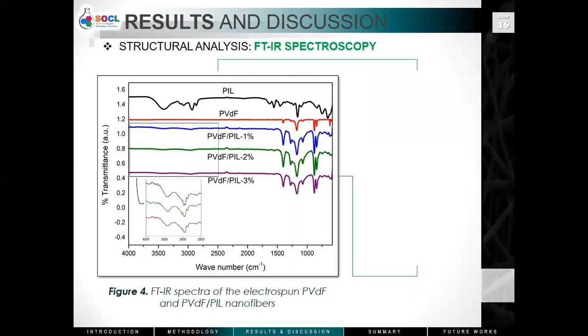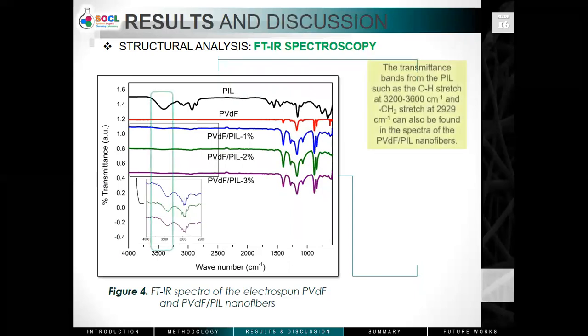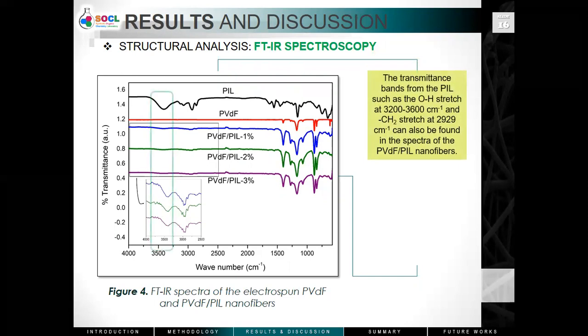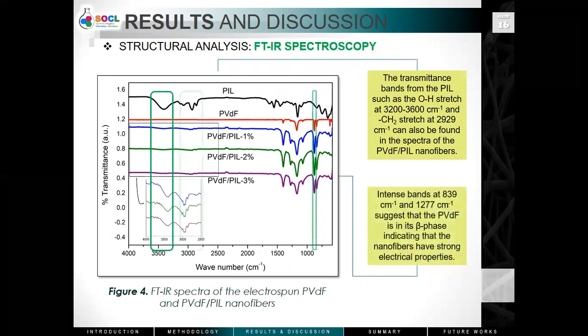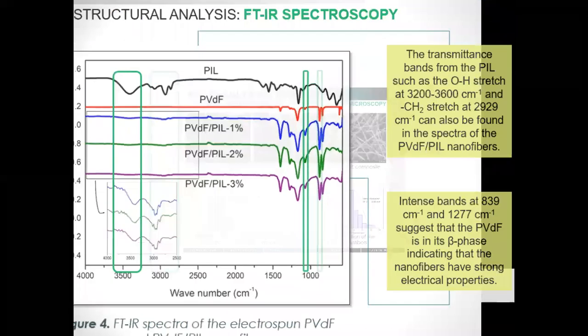As shown in this figure, transmittance bands from the PIL, such as the OH stretch and the CH stretch, can also be found in the spectra of the PVDF-PIL nanofibers. It can be seen that intense bands at 839 per centimeter and 1277 per centimeter suggest that the PVDF is in its beta phase, indicating that the nanofibers have strong electrical properties.